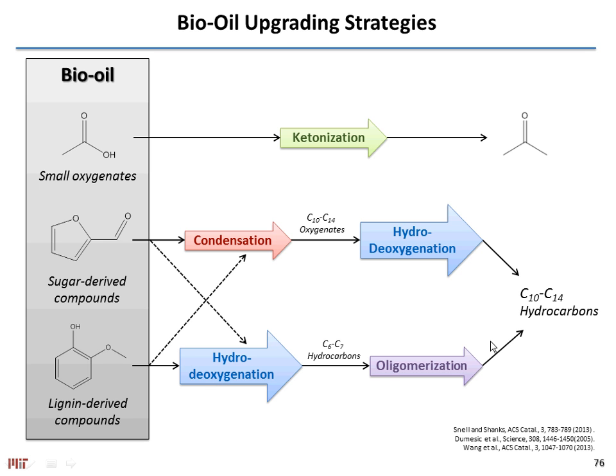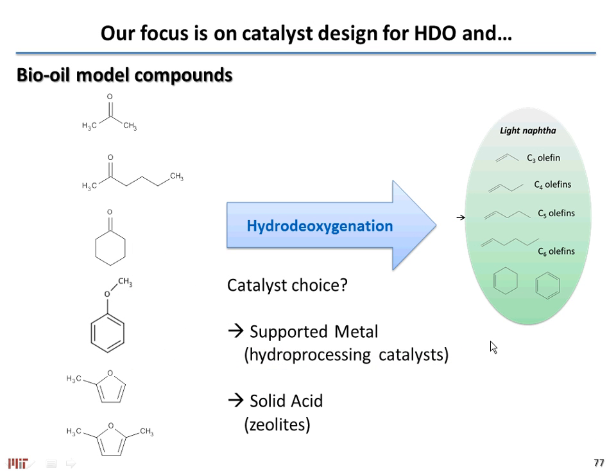And the idea would be then, rather than following the classic approach, right, of doing first a condensation, increasing your chain length by taking advantage of your molecular handles, and then doing your HDO and hydrogenation chemistry to get your final hydrocarbons, what we want to do then is do our HDO chemistry first over here, and then, by producing aromatics and olefins, do our known oligomerization chemistry to end up with this type of hydrocarbons over here that we can perhaps mix with the refinery. So of course, the question is, what catalyst would you want to use that would take any of these materials and perhaps convert them into a mixture like this? And that is not an easy question to answer, right? Because there are a lot of different cross reactions that you will have.